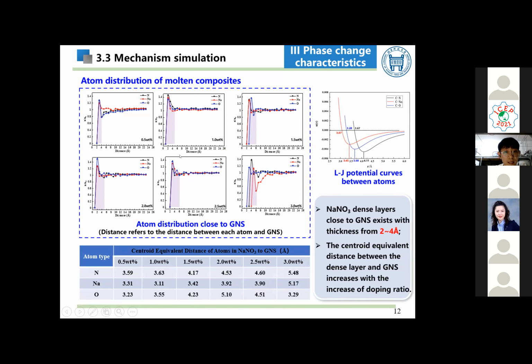We can see that there is a sodium nitrate dense layer of 2 to 4 angstrom. Besides, the centroid equivalent distance between the dense layer and GNS increases with the doping ratio. Considering that the interaction force between GNS and the sodium nitrate is only van der Waals force described by the Lennard-Jones force field, as the distance increases, the attraction between the two will first increase and then decrease for sure.